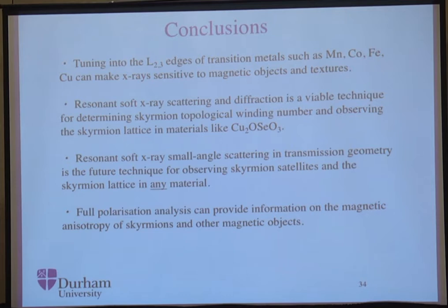Well, sorry, we were able to image the lattices. You can get the size, you can get the wave vector, and therefore the triangular lattice, but that's been known from the Lorentz TEM and from neutron small angle scattering. You're not learning that much more, unfortunately. I think you need to go down to the primary Skyrmion reflections, which are very, very close.